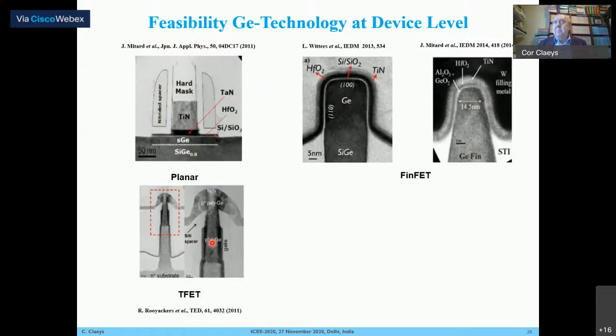You can also use germanium to make tunnel FETs. And in principle, you can make a germanium PIN structure. However, you don't want to do that. You want to have germanium in the source because you want to increase the tunnel probability, which is going to give you a higher drive current. But if you put also germanium in the drain, then you're going to get a higher leakage current. And of course, you want a very high on-off ratio for those type of devices.